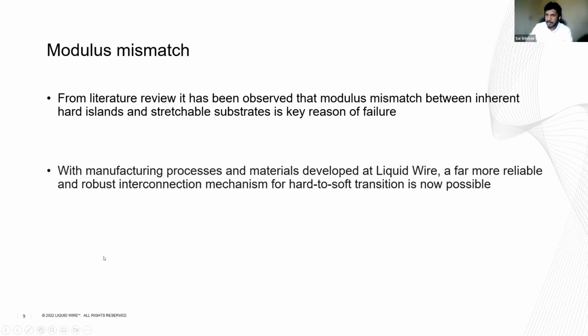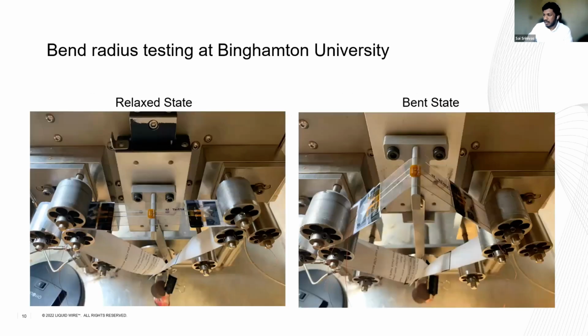From literature, we have identified that when you connect a flexible TPU structure to a surface mount or a PCB board, and when you stretch them, they break contact, or there's a scenario where you lose contact because of the modulus mismatch. But we have developed our proprietary process in such a way that you can stretch it 100%, bend it. You can even crease the components, but that would not break the contact.